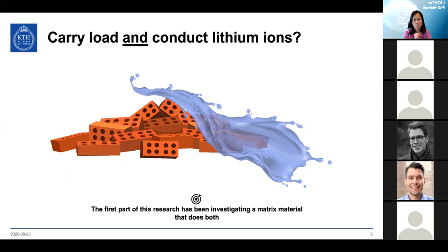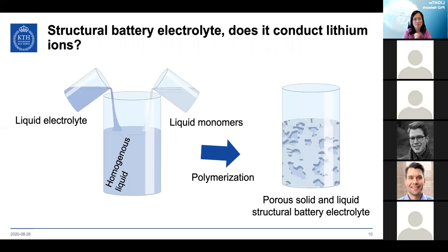First, let's investigate if the structural battery electrolyte can conduct lithium ions. The structural battery electrolyte is made by mixing a liquid electrolyte and a liquid monomer, both of which are specifically chosen to be soluble in each other, forming a homogeneous mixture. As the monomer begins to polymerize and solidify, the solubility changes and the two components separate into two distinct phases, like shaken oil in water. When the monomer solidifies, it creates a solid but porous backbone through which the electrolyte and lithium ions can flow.